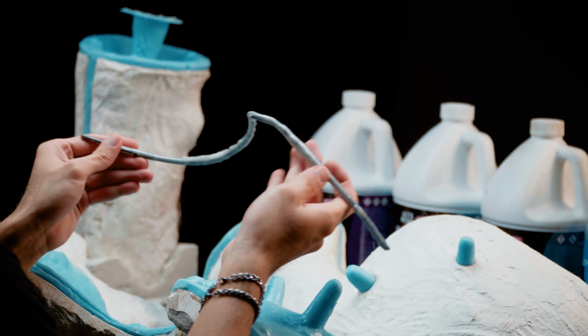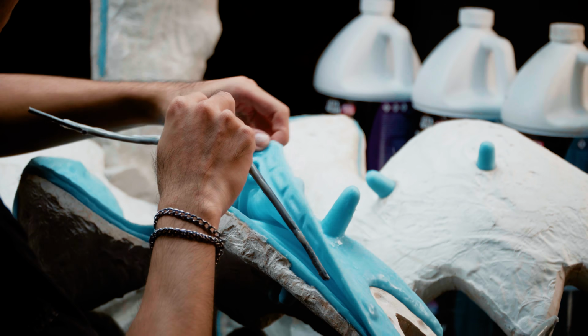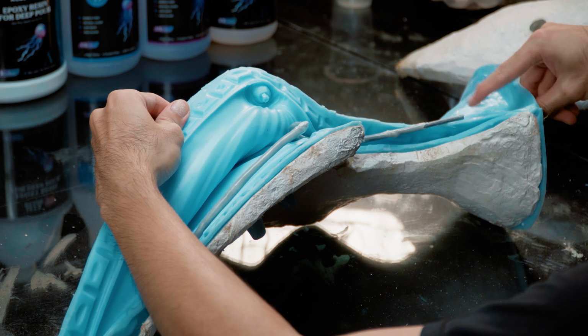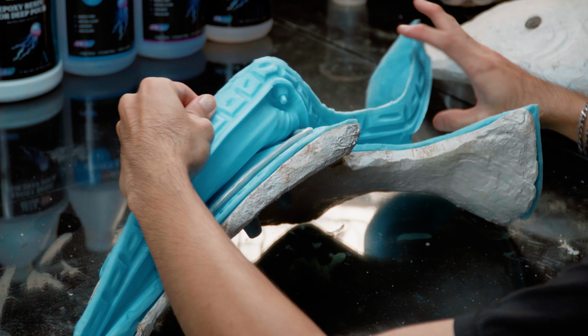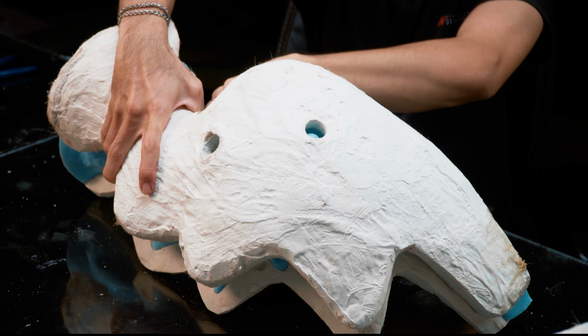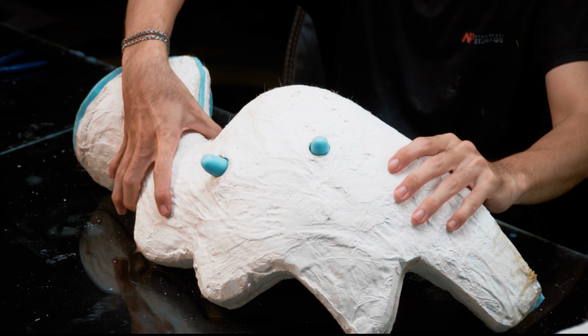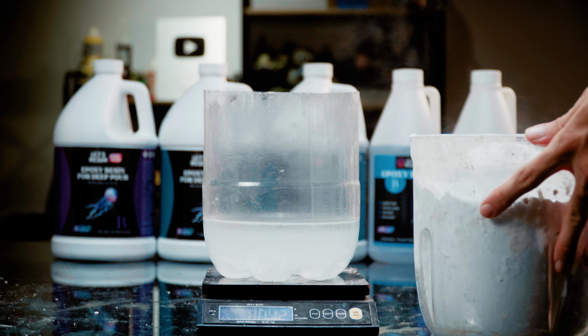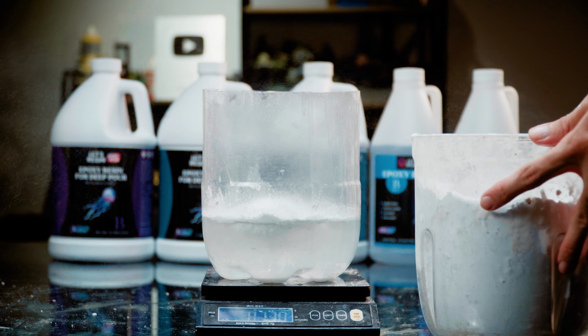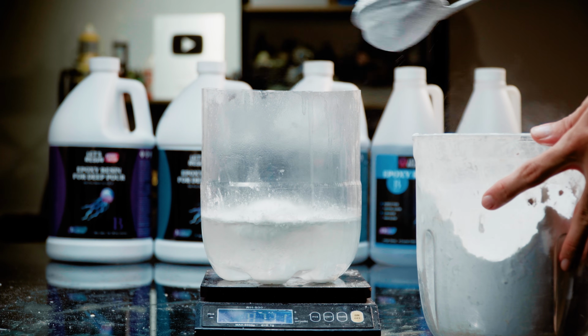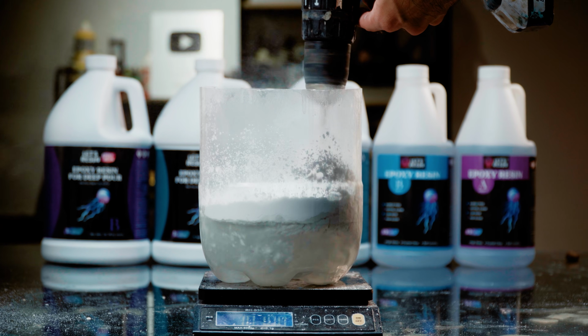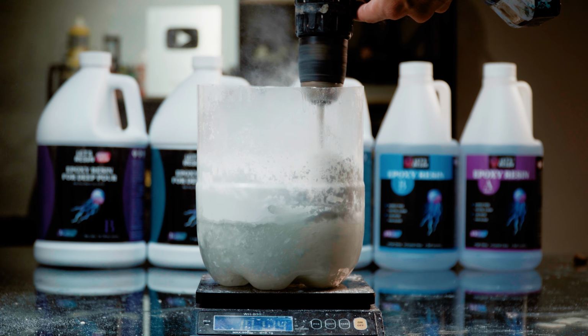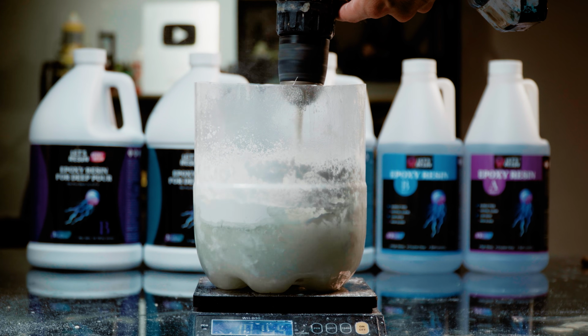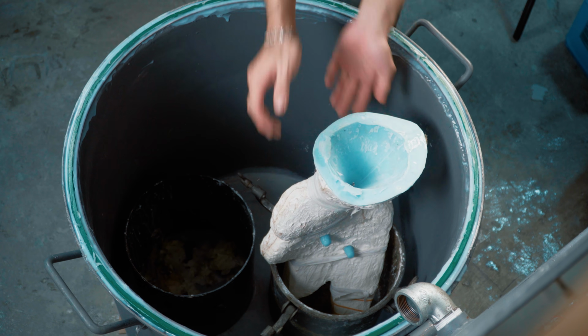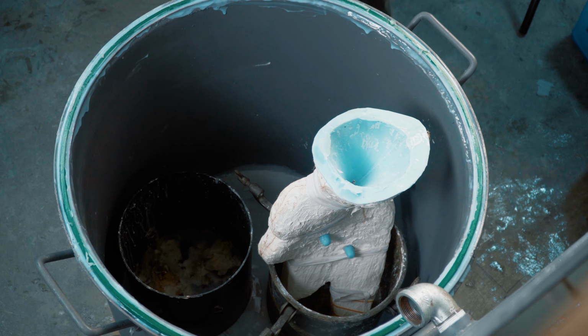Next, I will cast the wings. For this special part, I will reinforce it with a steel core placed inside the mold before pouring epoxy resin. With this load-bearing structure, even if the wings are wide and thin, they will not warp during use. This is extremely important because epoxy is flexible and elastic. Without a steel core, after a period of use or when the ambient temperature increases, the risk of warping is very likely to occur.